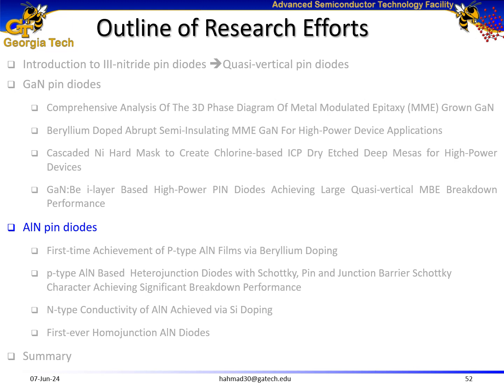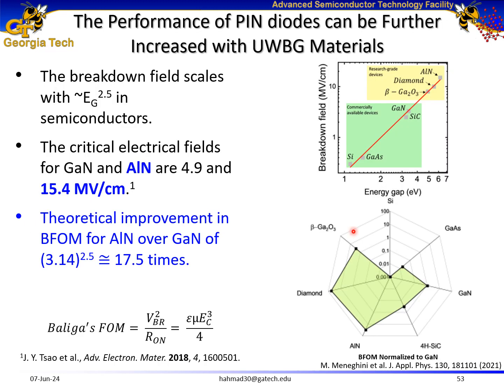So now I'm going to talk about my second pin diodes based study, which is aluminum nitride based pin diodes. The breakdown field of semiconductors scales with the bandgap of semiconductors, and we know that the critical electric field of aluminum nitride is approximately 3 times that of gallium nitride, resulting in a theoretical improvement in terms of Baliga's figure of merit for aluminum nitride over gallium nitride of approximately 17.5 times.